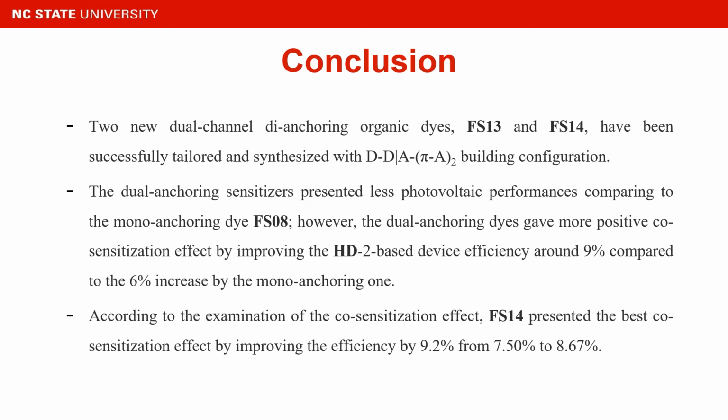According to the examination of the co-sensitization effect, FS14 presents the best co-sensitization effect by improving the efficiency by 9.2%, from 7.5 to 8.67%.